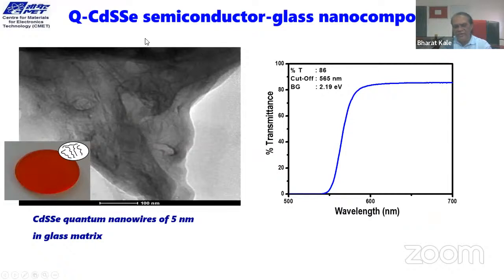Interestingly, what we found is that when CdS is doped in the glass and we change the thermal processing to a very prolonged thermal treatment, we observed that these 5 nanometer CdS nanoparticles get aligned and form nanowires. That's a very interesting thing we observe, and we are thinking about how we can utilize this. The transmittance is almost 86%. So nanostructuring in the glasses, and the formation of wires inside, will really help in some photonic properties.